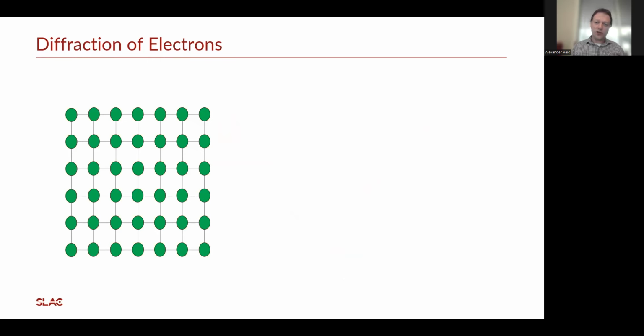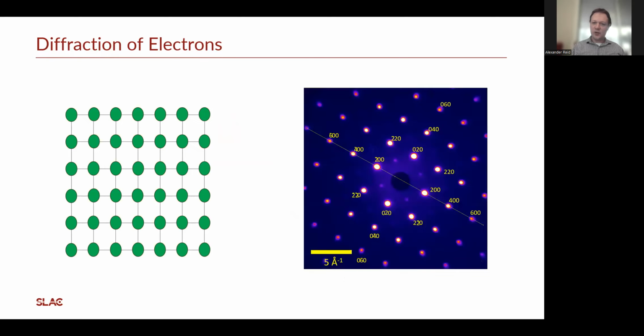So what does this look like in reality? For, say, a crystalline sample with a very simple lattice, what we end up with is this very typical Bragg-like diffraction pattern. So we get these intense areas of electrons around the center beam.